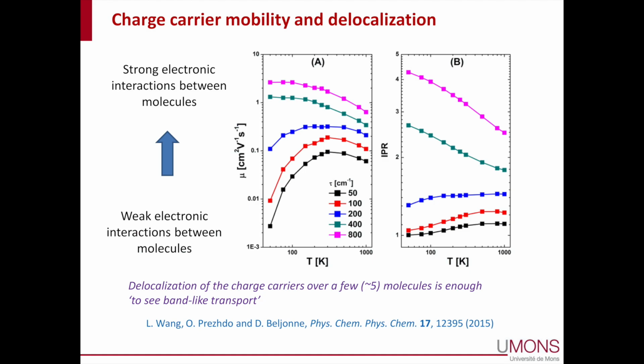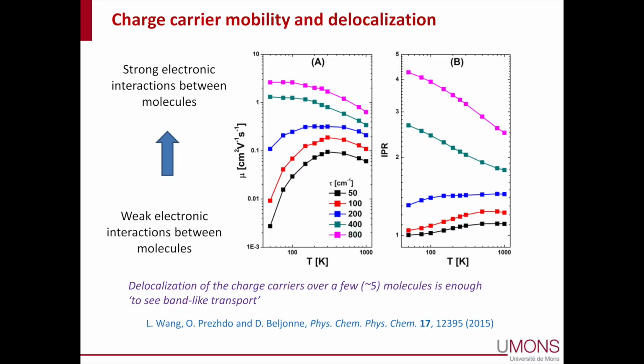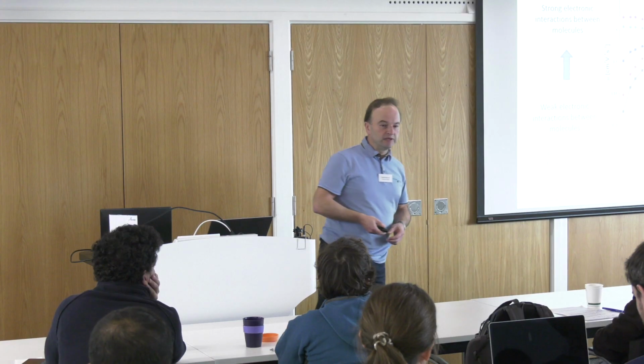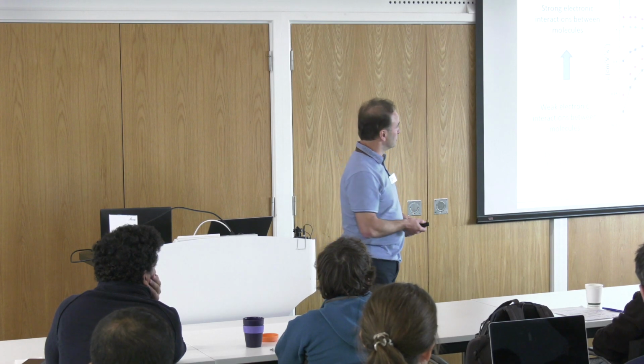Essentially we're using this model Hamiltonian, and what it gives is the charge carrier mobility along this one-dimensional stack, which is a good model for one-dimensional transport in organic crystals. We can predict the mobility versus temperature as a function of the quantum mechanical interactions. The parameter tau here is the transfer integral, a measure of how strongly the molecules interact quantum mechanically with one another. If you have weak coupling between the molecules, you get temperature-activated, hopping-like transport. If you go to much higher interaction between the molecules, you tend towards a power law behavior for the mobility, which decreases when you increase the temperature because you have more scattering with the phonons.